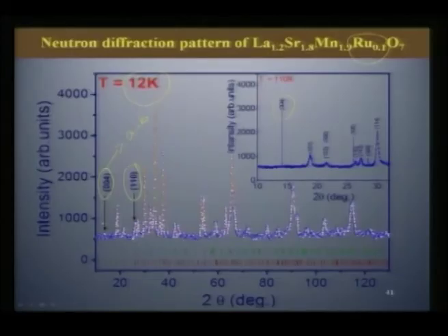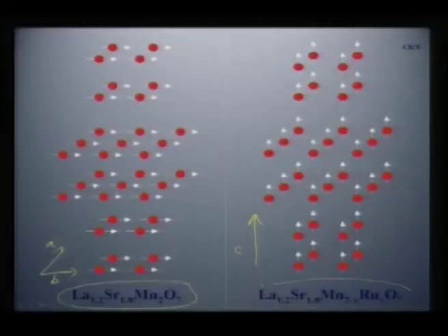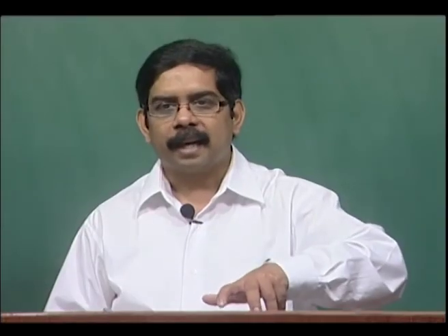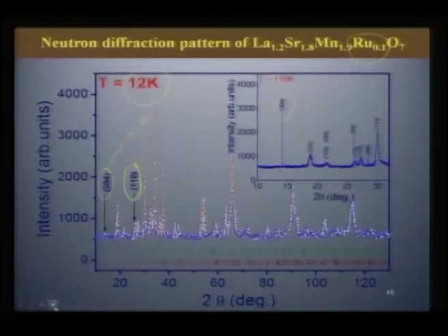Therefore, if it is turning more magnetic in the layered perovskite, this intensity should keep increasing. On the other hand, what happens in ruthenium is this is nearly absent and you have this 110 which is present, which means there is an interaction along the C axis. Nevertheless, we confirm this spin state. So, when you substitute ruthenium in the manganese site, you are actually rotating the spins' ferromagnetic alignment along the C axis. As a result, you are enhancing the properties.